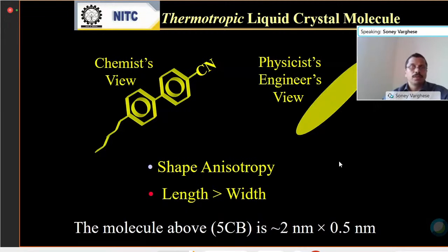And from a physics point of view, you can see that the molecule looks rod shaped. This is a rod-shaped molecule, and there is anisotropy associated with these molecules. You can see that the length is always something like 2 nanometers, and the width can be around 0.5 nanometers.